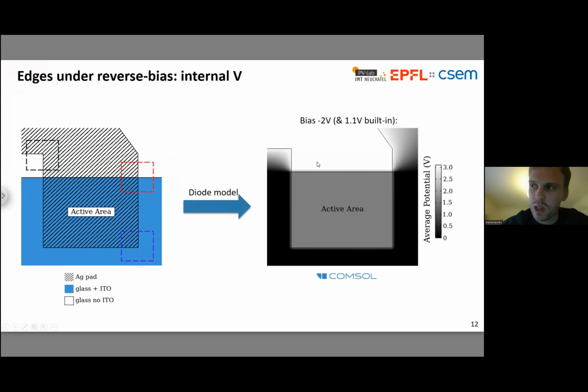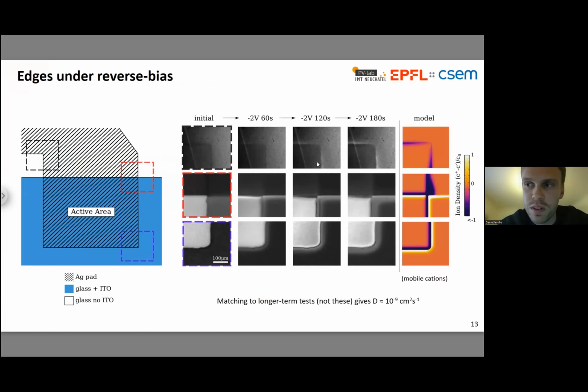And then you can go one step further and use that computed potential to drive a drift diffusing ion simulation. So that's now what I've done on the right-hand side. Basically, I've taken that potential, I've driven an ion for a certain amount of time, and I'm showing you the comparison between the experimental PL images and the distribution of ions on the right-hand side. So you can see that it's not an exact match, but there is some confirmation here, at least, that all the features we see in this experiment could be explained quite plausibly by laterally diffusing ions.